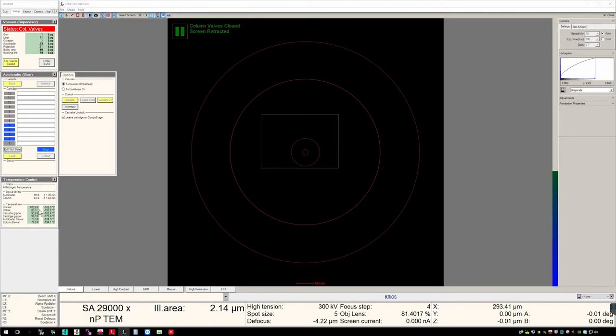So when all three of these are at a proper temperature, devitrification occurs at -143°C, so any temperature lower than that is good, but we want to be extra sure, and in order to do that, we wait for around 100 Kelvin. The Dewar has now cooled to under 100 Kelvin, and I am going to begin the inventory. We'll press the inventory button and watch the automated procedure complete.